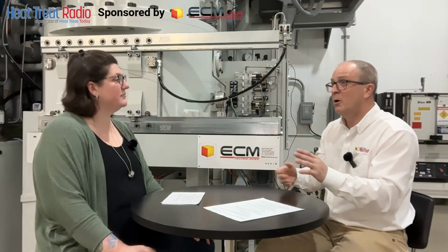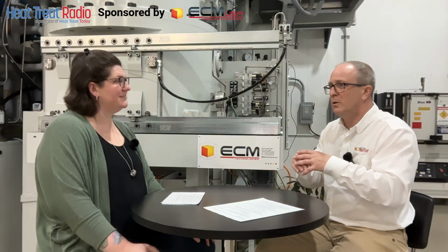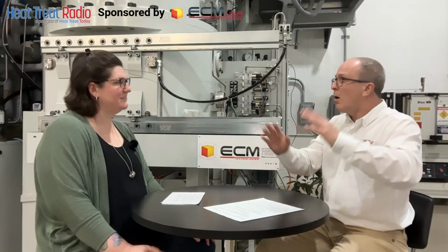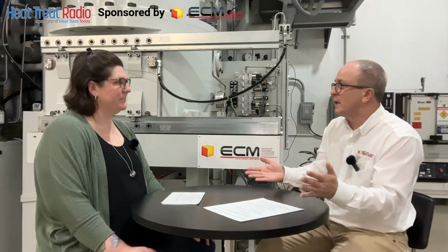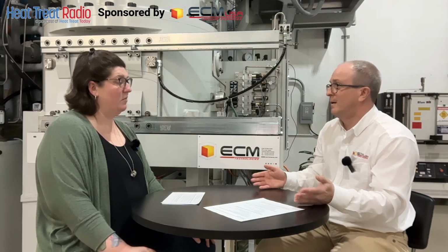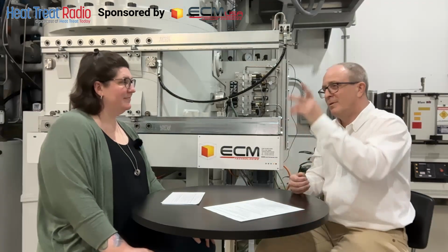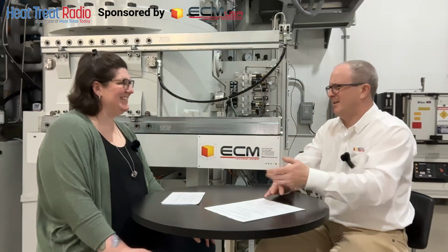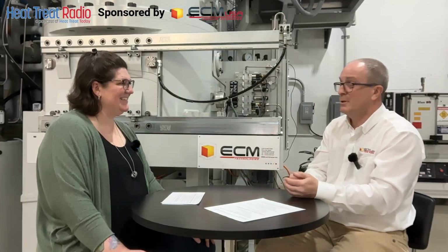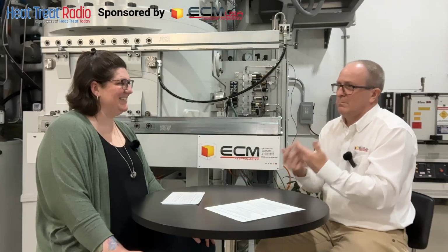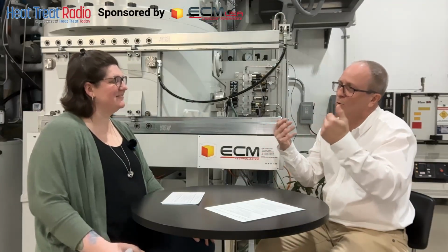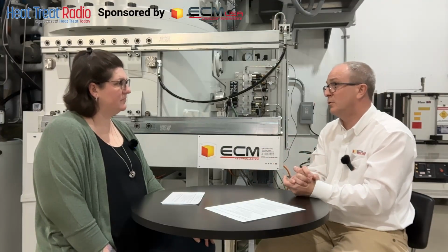Okay. And we found that you don't crack with gas quench. Whatever the pressure, we never have really much a crack, or a customer say, oh, the part break due to the gas quench. Never happened. Wow. There was a question of the competition, and I said, did you ever see a crack with gas quench? No, because it's the way the gas quench cools down the part, it's less strong than the liquid, so you don't have this potential issue.